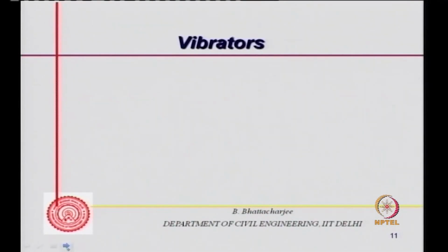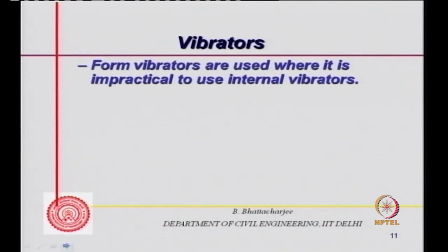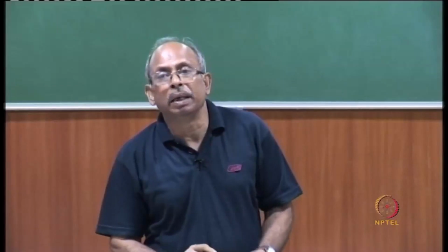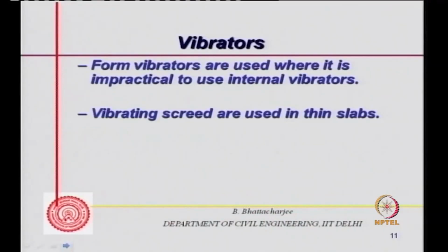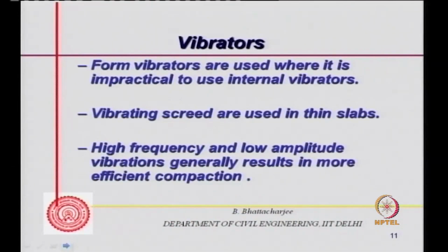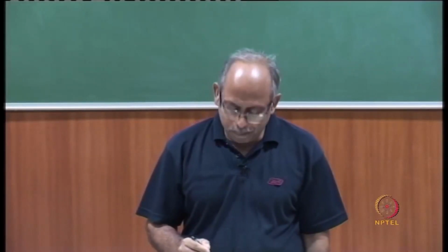So we have seen where we select the needle vibrator of what dimension. Now we can look into form vibrators. Where do we select them? Where it's impractical to use internal vibrators, or where it might be supplementing the internal vibrators. Vibrating screeds are used in thin slabs. High frequency and low amplitude vibration generally results in more efficient compaction. So the thinnest of the needle vibrator actually is most effective, but its radius is also low. So your effort in moving this will be relatively high.